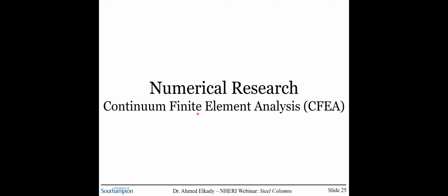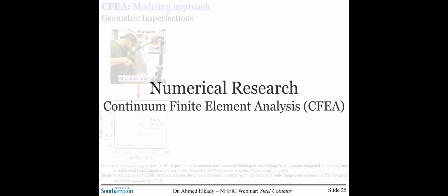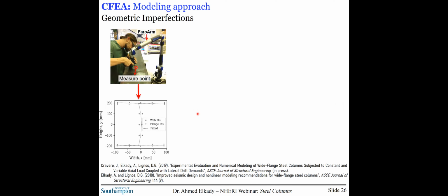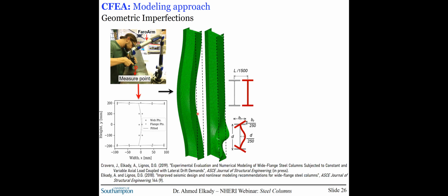The second phase of the research involved parametric continuum finite element simulations to generalize the test findings and to fill the gaps within the experimental data pool. First, we had to develop a robust finite element modeling approach that is defined in an objective manner and that's not biased by test-specific calibrations or model tuning. So this was done systematically. First, we investigated several column members by measuring the local and global geometric imperfections that are a product of the rolling process. These mean imperfection values are then deduced and considered in the finite element model.